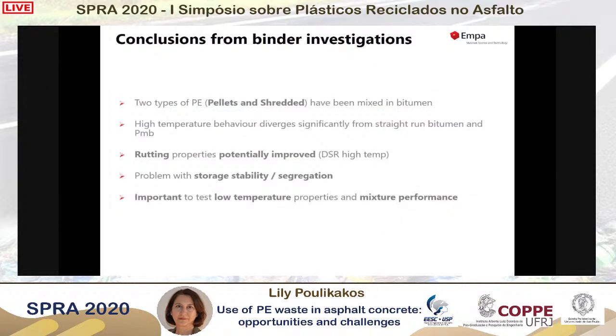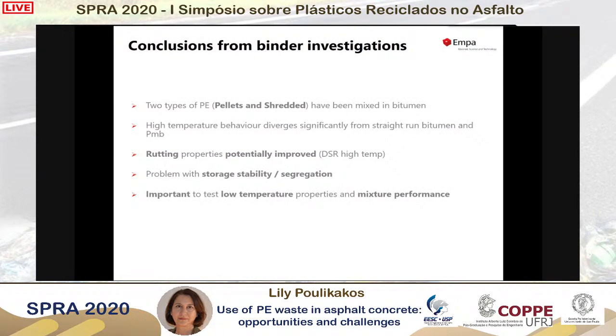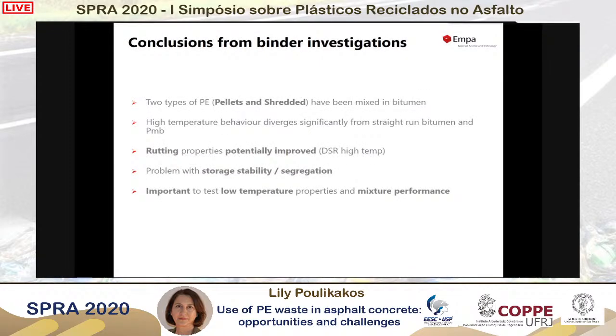So what did we learn from the binder investigations of these two types of PE waste materials? We have seen that there is certainly a divergence in behavior at higher temperatures from the base bitumen and from polymer modified bitumen. The higher modulus values could be a reason that we could use this material for improved rutting performance. And we also saw that there's a storage stability problem and a segregation problem. We also would like to emphasize that the low temperature behavior needs to be studied further.